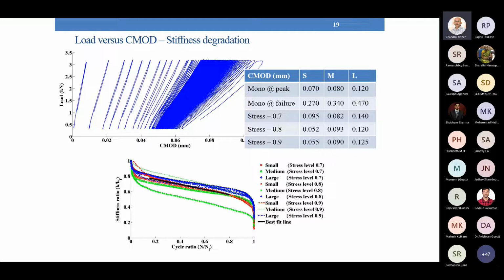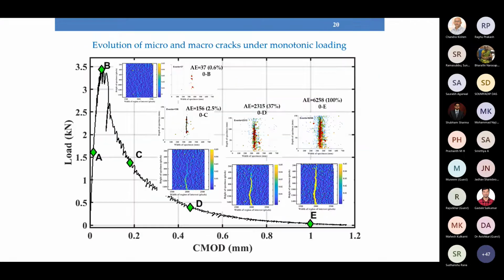a failure criteria. Now here, this is a softening curve which was missing in the last one. So here I have both the digital images and also the acoustic emission results. These dots in the acoustic emission are events, and we have different sizes of these dots. The blue are different size or different colors. The red one is the largest. The sizes are classified based on the energy of an AE event.